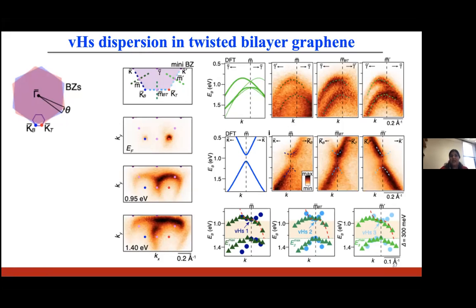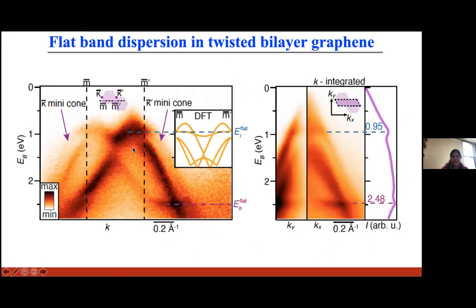And so next, I'm going to show here the ARPES intensity cuts along the M prime of the neighboring Brillouin zone. And what we see is a flat band observed around the superlattice Van Hove singularity at a lower binding energy, and we see another flat band at a higher binding energy.